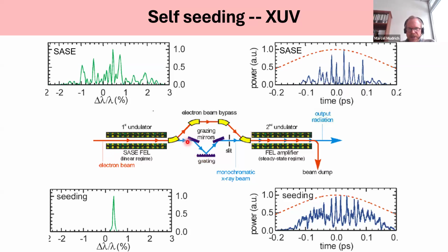And as long as we are talking about 10 nanometers or 100 nanometers, then we can use artificially fabricated gratings, because using nanotechnology we can fabricate 10 or 100 nanometer groove spacings. But if we are talking now about X-rays, which corresponds to angstrom wavelength, then we need angstrom lattice constants for the grating, and so this is single crystals.